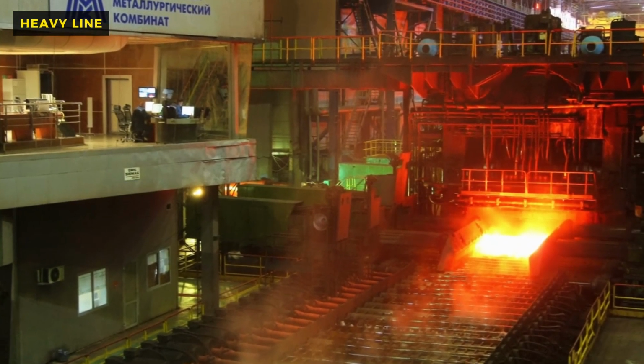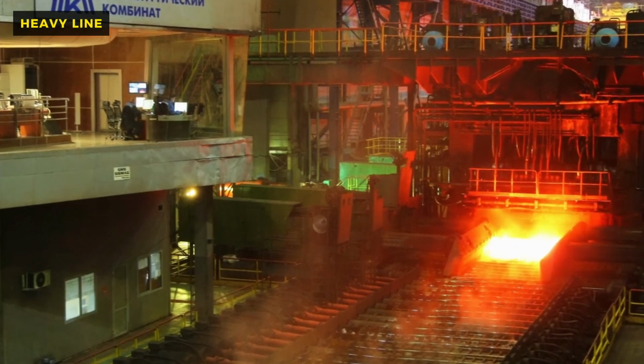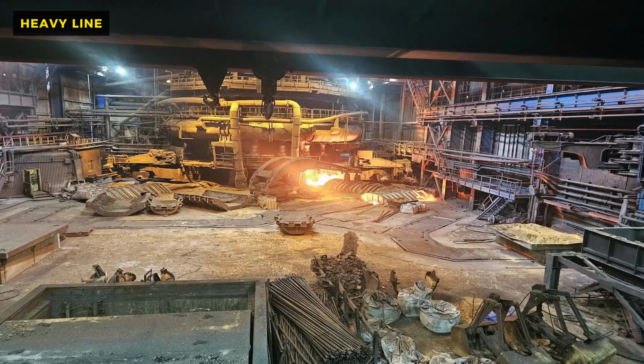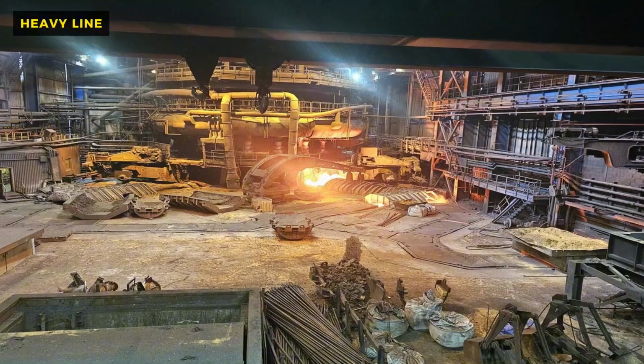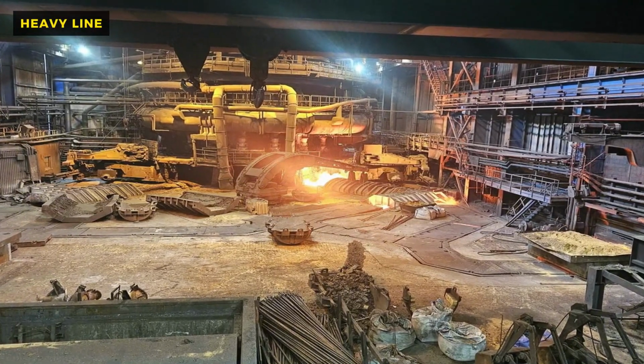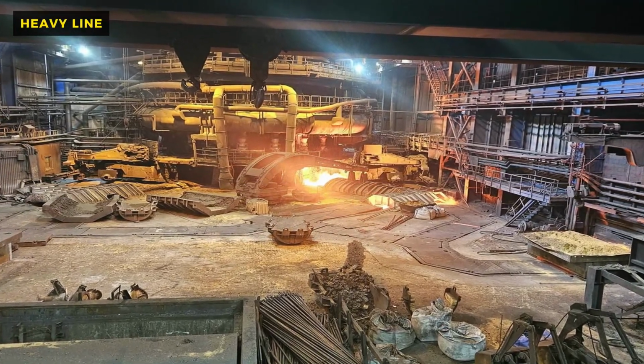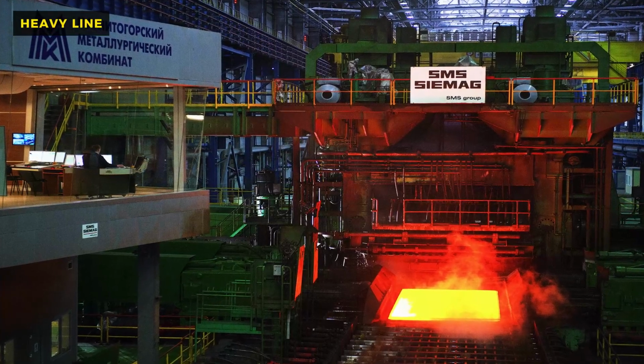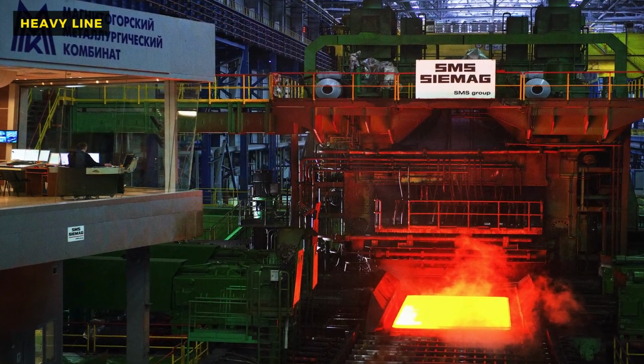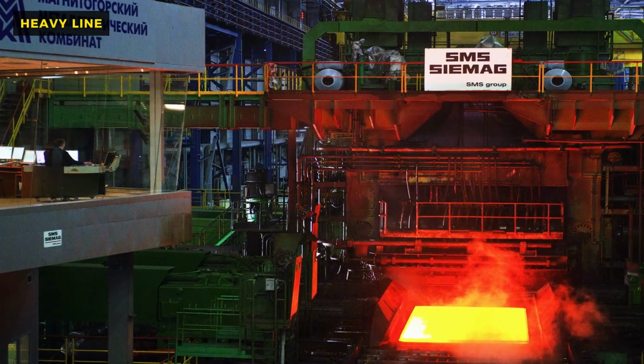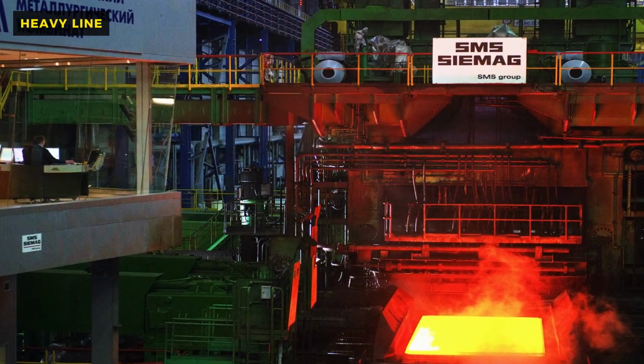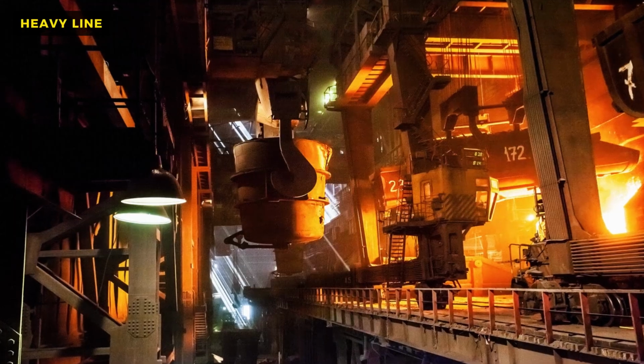This lance blows pure oxygen at supersonic speeds directly onto the surface of the iron. The effect is instantaneous and violent. The oxygen reacts with the carbon in the iron, burning it off as carbon dioxide. This is an exothermic reaction. It generates its own heat. The temperature inside the vessel spikes, boiling the metal.